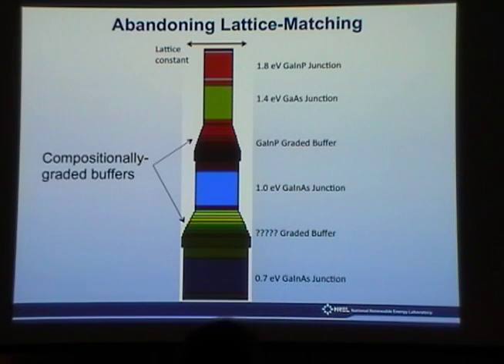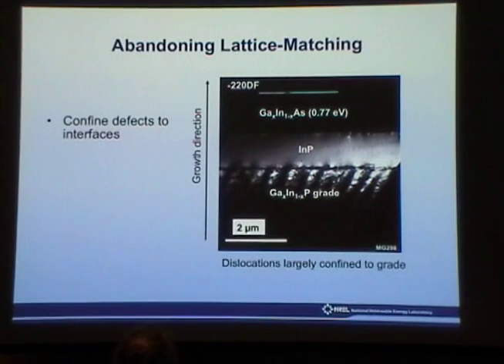Okay, so let me move on. Here's a TEM. It's clear on my screen. Here's the growth, and what you have is a gallium phosphide graded layer, followed by an indium phosphide material and then gallium arsenide material. This is the solar cell, and this is sort of an intermediate layer. And what you can see here, if you look carefully, is that this is chock full of defects. There are many, many layers in that grade, and we're slowly changing the lattice constant. And it's chock full of defects.